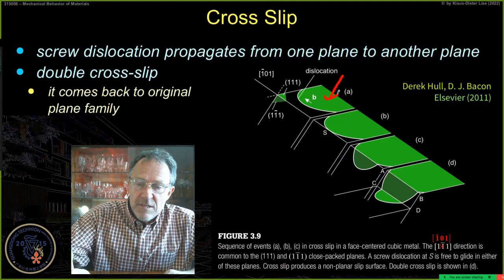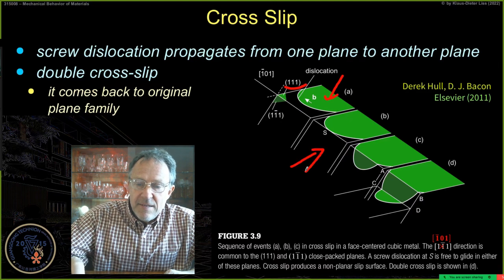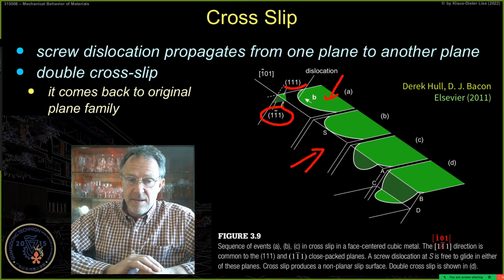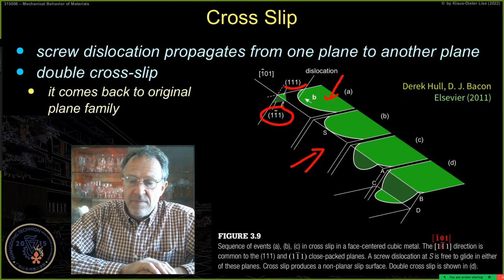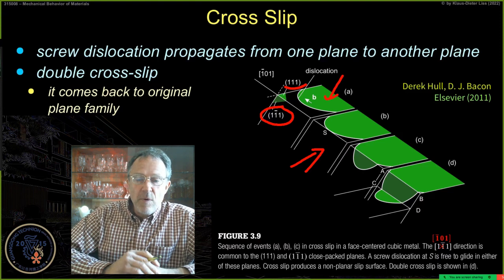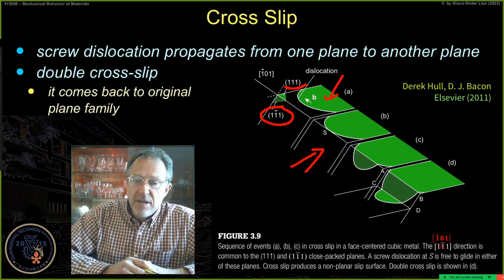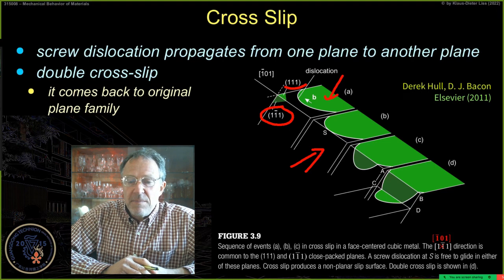Crystallographically, this is a slip plane here, which is the 111 plane, and this is another slip plane, which is the 1-1-1 plane. Particularly in a cubic system, so FCC lattices, where the slip occurs on 111 type planes, they are the same type of planes. They're only different by the orientation, but the local symmetry, the local environment is exactly the same.